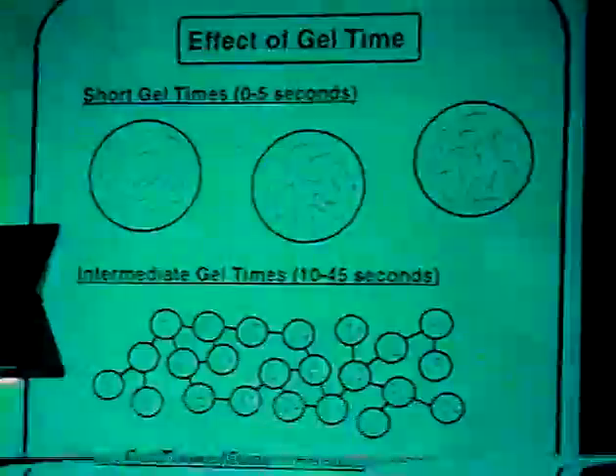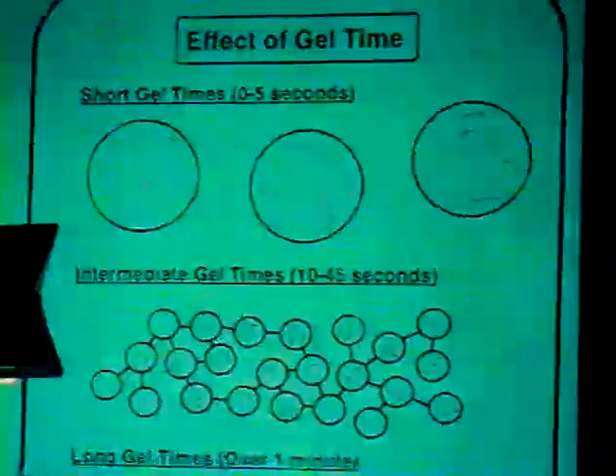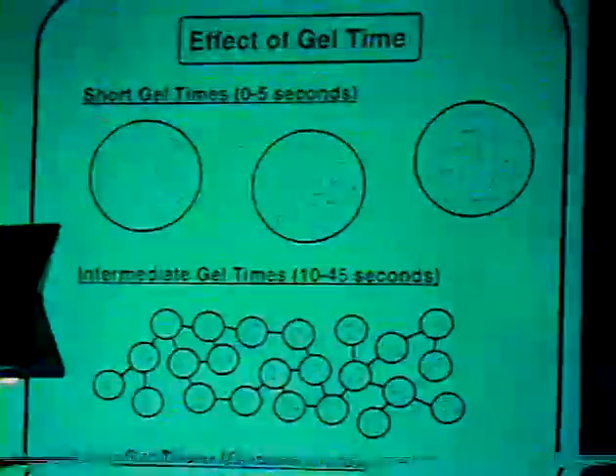Think about the problem the following way then. By controlling the gel time, we now have a unique way to bring materials out of the solution of different quality, in terms of the size of the particle as well as the defect density within those particles. So what we think happens is the following. With short gel time samples, by that I mean anywhere from 0 to 5 seconds, we just have precipitate come out of solution with large particles, and the fact that they come out of solution so rapidly means that they have a lot of defect density, which facilitates the transformation upon heating. And this is the one sample that even at 973K, totally converts into monoclinic form.